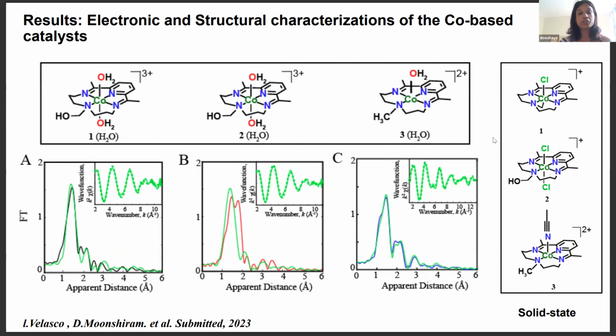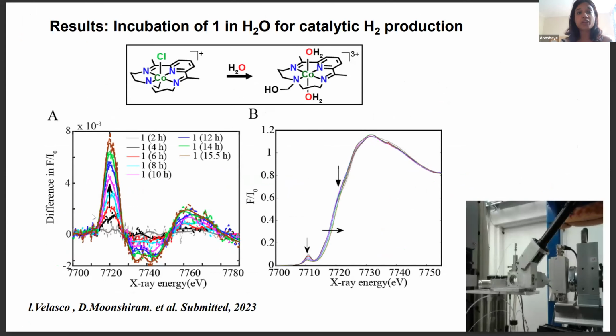And the EXAFS were also measured, which showed a prominent peak within the first coordination sphere corresponding to the average contribution of the cobalt-nitrogen and the oxygen distances from the aqua molecules. So this provided us with a first basis of how our catalyst structural conformations are prior to light excitation. So upon light excitation, we have the typical MLCT process from the 4d orbital to the pi-star orbital of the ruthenium photosensitizer, followed by intersystem crossing to the formation of a triplet excited state. And this triggers electron transfer from the cobalt-3 to form the photoreduced cobalt-2 intermediate.